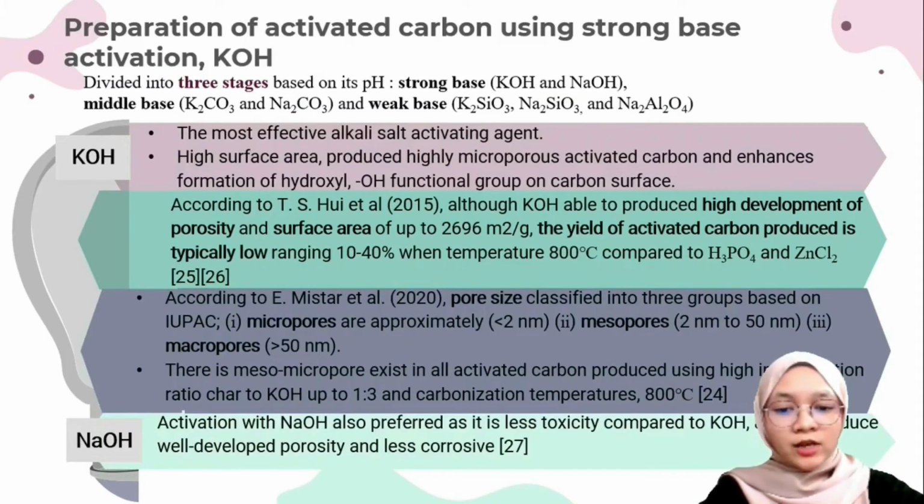Potassium hydroxide activation can be performed in three stages. The first one is the products from the carbon gasification, which are water and carbon dioxide, which initiate the pore development. And then the second one is the production of potassium oxide and potassium carbonate when the temperature reaches 700 degrees Celsius, which introduces a carbon skeleton to develop the pore framework by redox reaction. The third stage is production of potassium metal at a temperature of 800 degrees Celsius, which diffuses and incorporates into internal pores of carbon. As a result, new porosity develops and the existing pores expand.